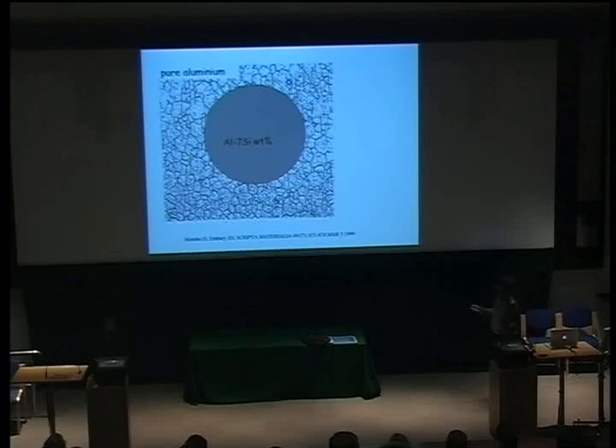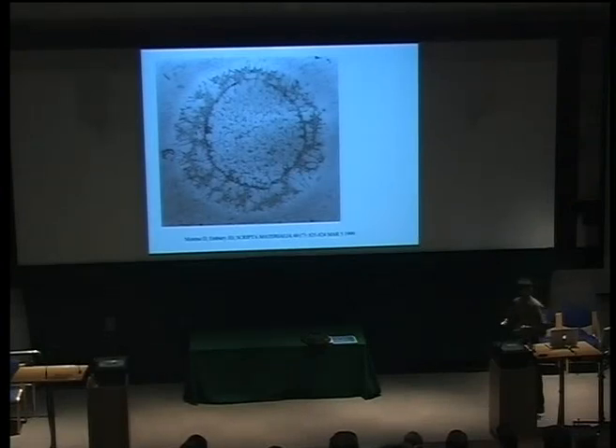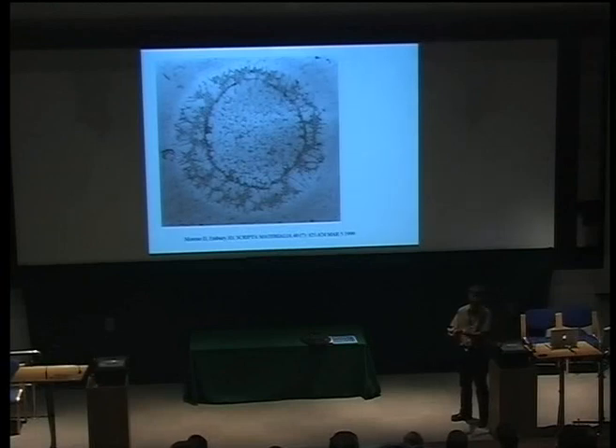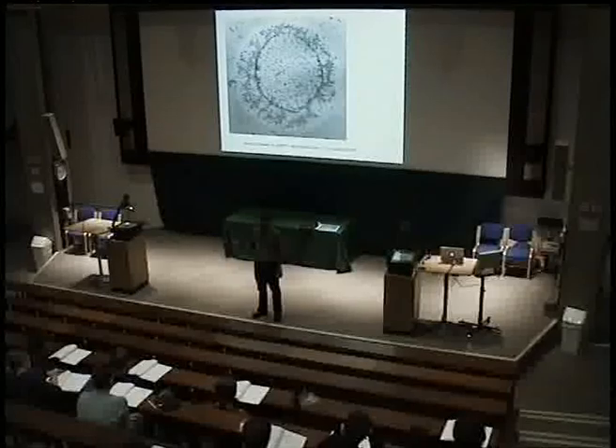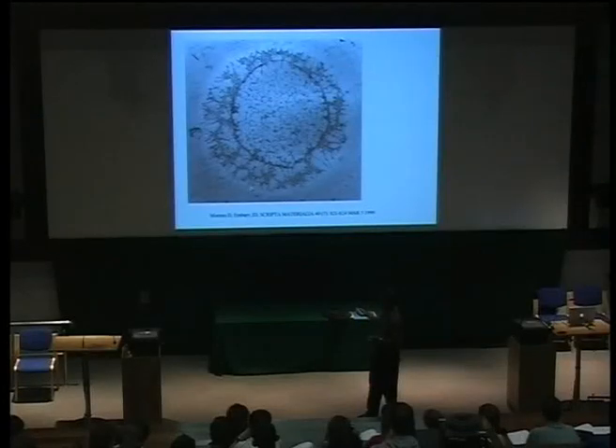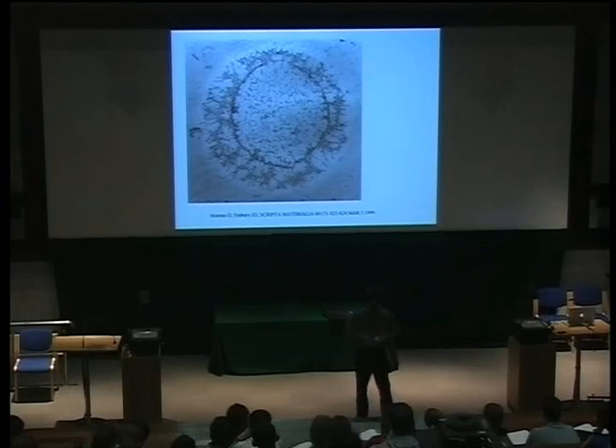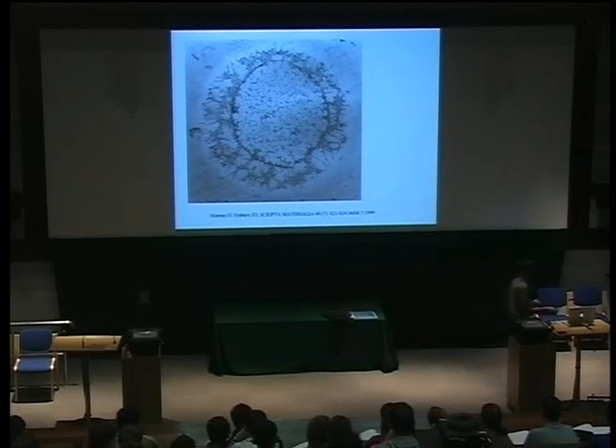Here is an example where an aluminum-silicon rod was put into a pure aluminum matrix. After diffusion, solute is moving along the grain boundaries because those are regions with large free volume. You might argue we don't need to worry about lattice diffusion since the easiest path is the grain boundary. However, the vast majority of atoms are not located at grain boundaries — they're in the perfect crystal regions. So although diffusion is easier along the boundary, the fraction of material there is much smaller, and we must look at fluxes through both regions.